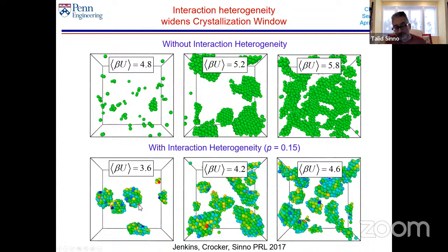And it's because having the heterogeneity actually stops the system from gelling. It's kind of an inhibition of gelation. The reason for that is that the strong binders recruit particles first, while the weak binders are still not yet driven to aggregate. And so instead of having nucleation take place all at once, it spreads this nucleation process out. So this is another situation in which, when I have a non-equilibrium situation where I'm growing crystals, something has a real world effect. In the first case, it was hydrodynamics. In this case, it is heterogeneity across particles. I inhibit gelation and I make crystallization more robust.